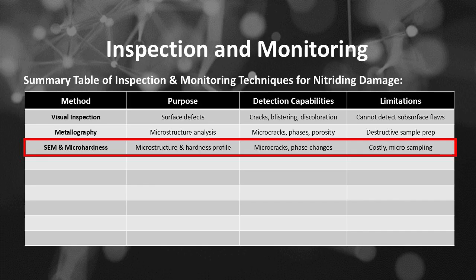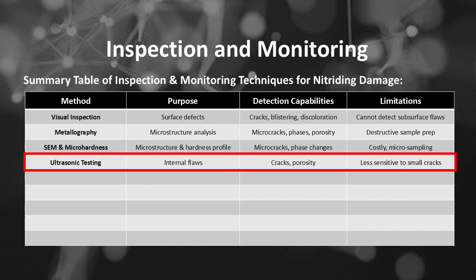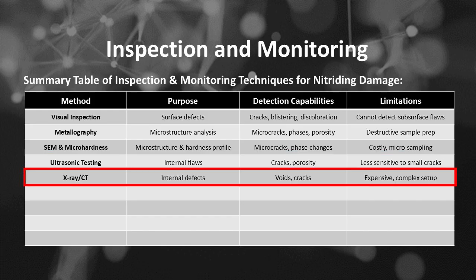If the method in use is scanning electron microscopy, SEM, and microhardness, its purpose is microstructure and hardness profile, its capability is to detect microcracks and phase changes, and the limitations are cost and microsampling. If the method is ultrasonic testing, its purpose is internal flaws, its capability is to detect cracks and porosity, and the limitation is less sensitivity to small cracks. If the method is X-ray radiography or CT, its purpose is internal defects, its capability is to detect voids and cracks, and the limitations are expense and complex setup.